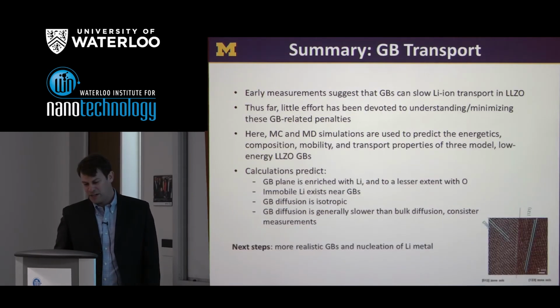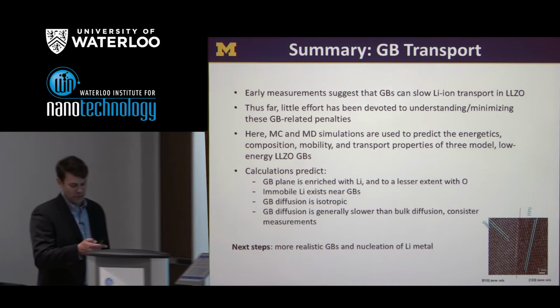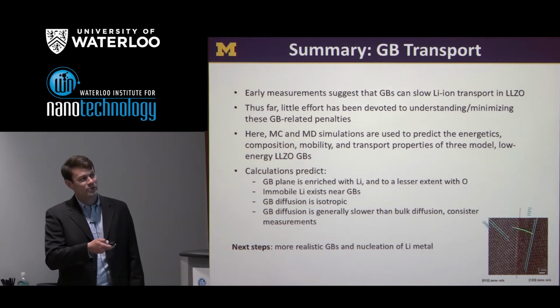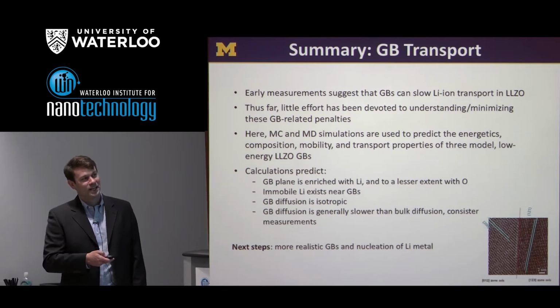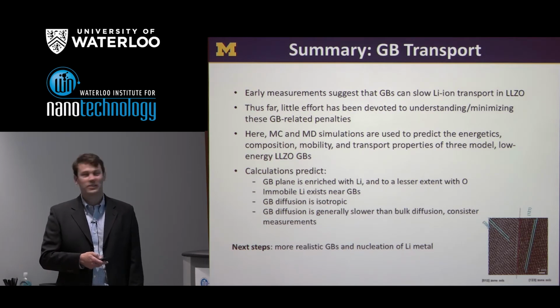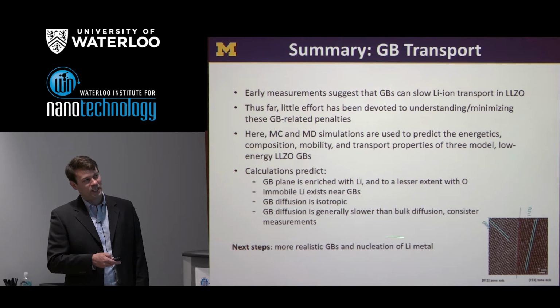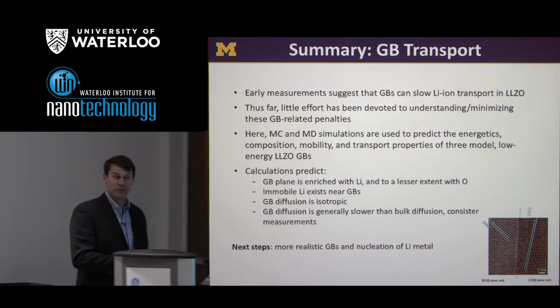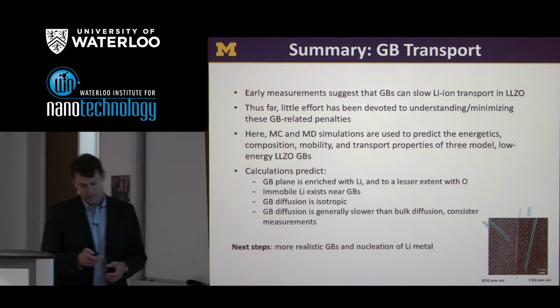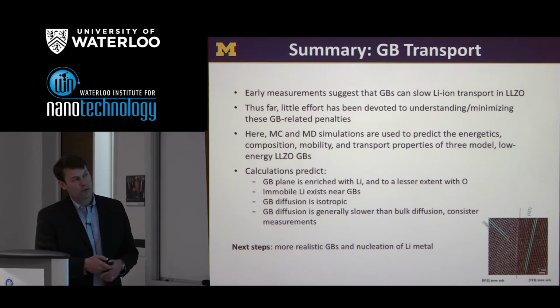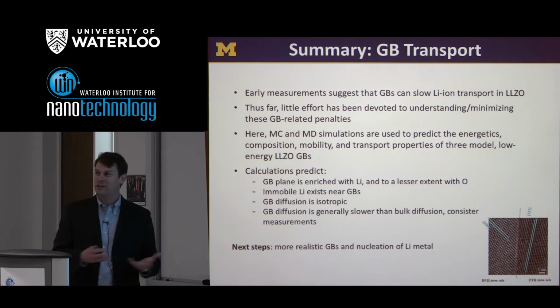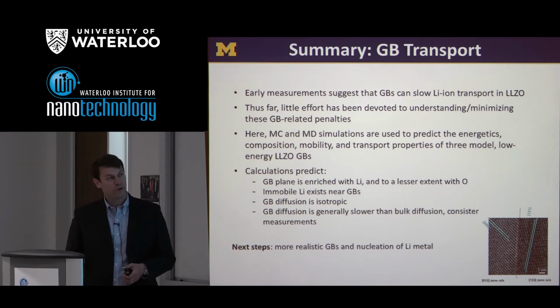So what we're thinking about now is, well, here's a realistic and quite ugly grain boundary that we've got from Oak Ridge. This is something in principle we could run a calculation on. In fact, we've mapped the atom positions and built an atomic scale model. It's not a pretty system to calculate. But probably more interesting is to look at the nucleation of lithium metal, and this comes back to those dendrites penetrating the grain boundaries, to understand what is the thermodynamic driving force and the mobility of, rather than lithium plus, lithium metal, as we form these dendrites.